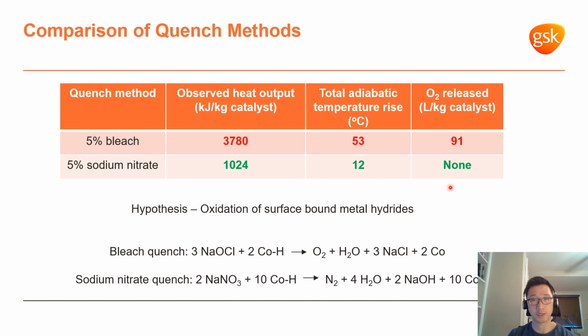And so what we think is happening in both quenches is that we're oxidizing the surface-bound metal hydrides to deactivate the catalyst. But with bleach, what happens is that we're producing oxygen, whereas with sodium nitrate, we just produce some nitrogen, which we know is inert. We also see how much more efficient the sodium nitrate quench is. We see that 2 moles of sodium nitrate can quench 10 moles of the cobalt hydride, whereas with the bleach quench, it takes 3 moles of sodium hypochlorite or bleach to quench 2 moles of cobalt hydride.